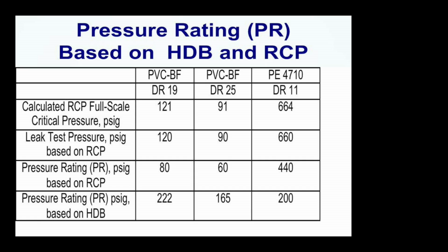In the case of polyethylene, the critical pressure is 664. We don't leak test pressure this high, but it could have a leak test pressure as high as 660. With a pressure rating of 200 psig, the actual pressure test is 300 psig. That's where 200-pound polyethylene would be leak pressure tested. But again, the actual pressure rating and the leak test pressure are considerably lower than the critical pressure.